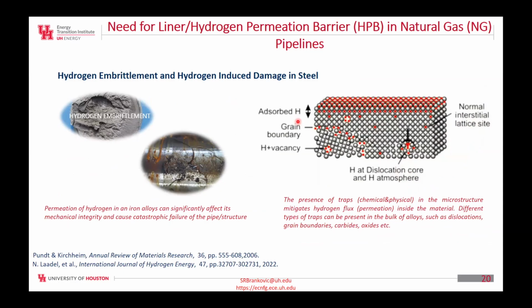It's a serious problem, especially in the nuclear industry, because those are high temperature problems. But whenever we're talking about high strength steel used for typical pipe networks, this is even worse, because even at room temperature, hydrogen permeation results in decarburization of the steel and catastrophic failure. Therefore, to battle this, you can reduce the pressure, reducing the capacity of the pipelines. You can blend the hydrogen, which then has to be separated through membranes. But overall, if you can use pure hydrogen under high pressure, your pipelines will be most efficient, and that requires some modifications.